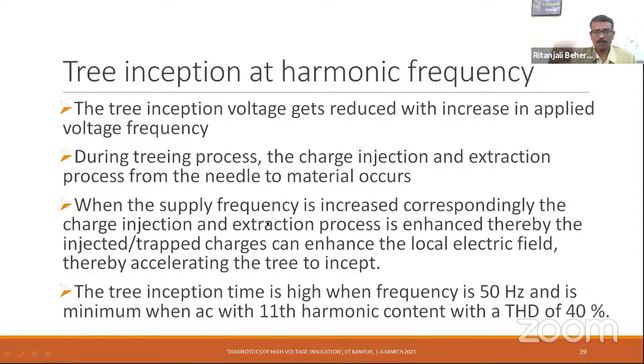Tree inception. In fact, I should have spoken about this a little earlier. The tree inception voltage gets reduced with the increase in the applied voltage frequency. During the treeing process, the charge injection and extraction process from the needle to material occurs. When the supply frequency is increased, correspondingly, the charge injection and extraction process get enhanced. And so the injected and the trapped charges will enhance the local electric field at the tip, which causes the tree branch to incept. So the tree initiation time is high when the frequency is 50 hertz power frequency, and becomes very less, a minimum, when it is present with 11th harmonic content with the THD of about 40%.